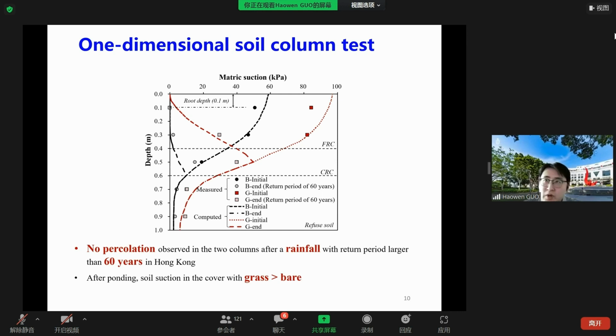So after the ponding, the measured matric suction in the bare column reduced significantly, whereas a relatively high suction, such as at 0.1 meter and 0.3 meter in the grass column, was preserved. So this shows that after rainfall with a return period of 60 years, the capillary barrier in the grass column is still active, while that in the bare column has failed. The results show that the cover system using recycled concrete can enhance the performance of the cover.